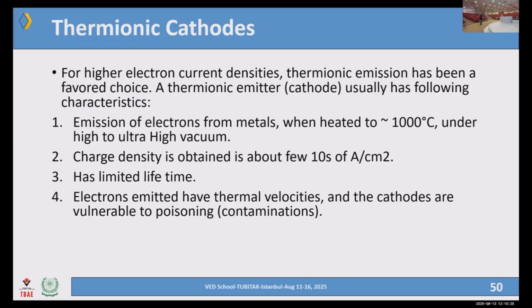When we had some accident, the vacuum got lost, meaning it exited the extreme ultra high vacuum or ultra high vacuum range and went to the high vacuum range, meaning thereby that if you have a vacuum operating at 10^-8 millibars or 10^-8 torr, it jumps to, let's say, 10^-6. Even if it's still a vacuum, it's a reasonably good vacuum for many applications, but it is the dead end for your gun. So the pressure at any cost must not exceed 10^-6 millibars. This is the upper limit.